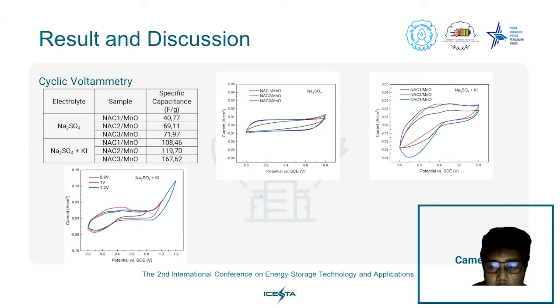For the NAC3/MnO here, we add some potassium iodide to make the specific capacitance bigger. You can see here in the graph, I mean the curve, that the addition of potassium iodide makes a redox reaction here compared to without potassium iodide. The potassium iodide that we use here is 0.05 molar, and for the Na2SO4 it is 1 molar. Then after that, we varied the voltage, and at 1 volt you can see the peak here, and at 1.2 volt here we can see the peak too.